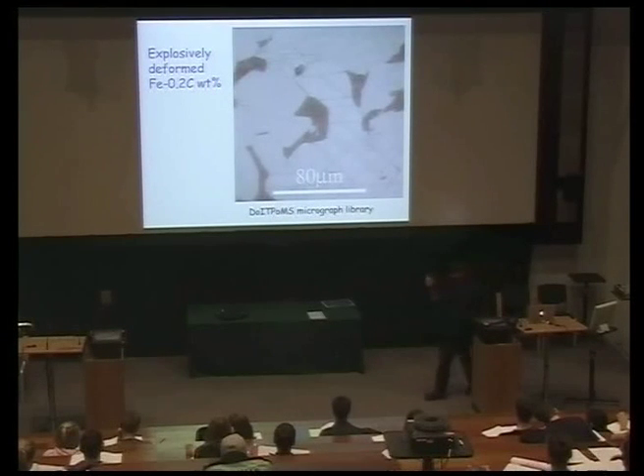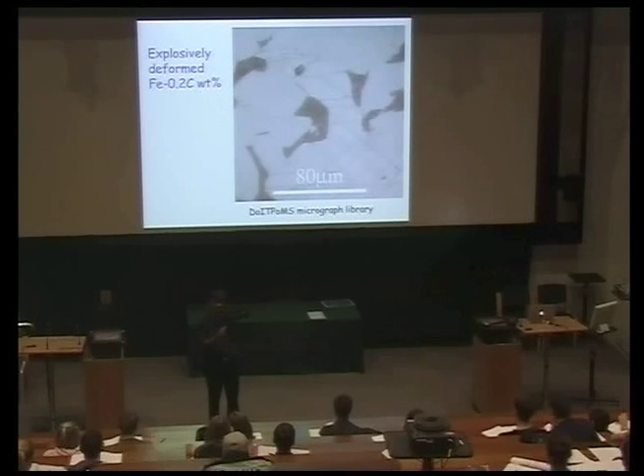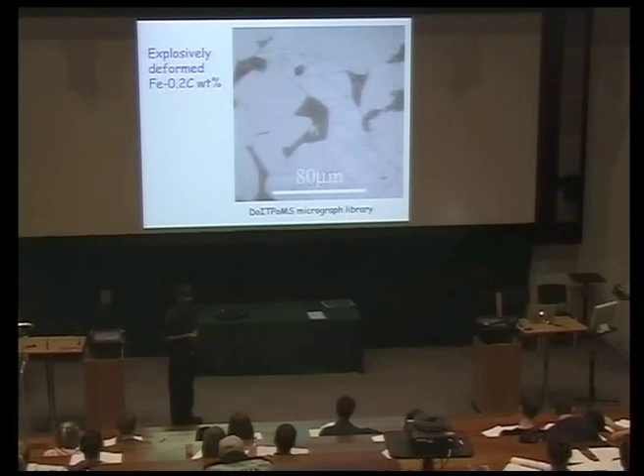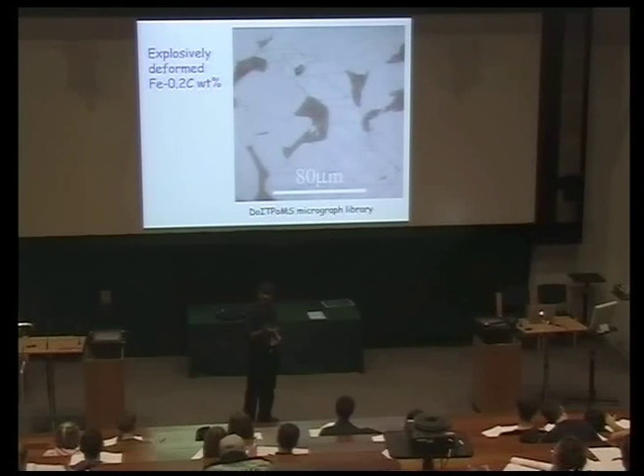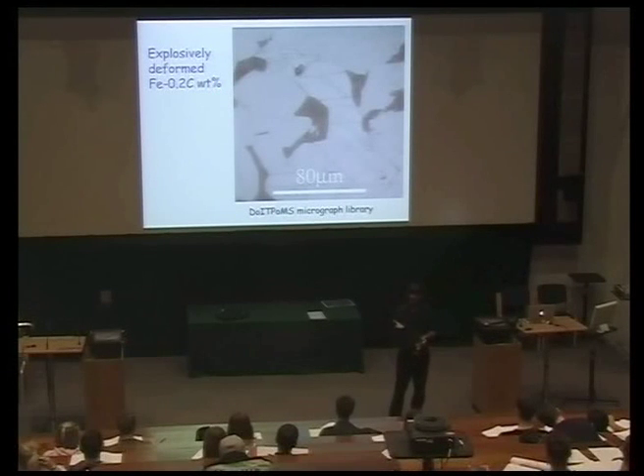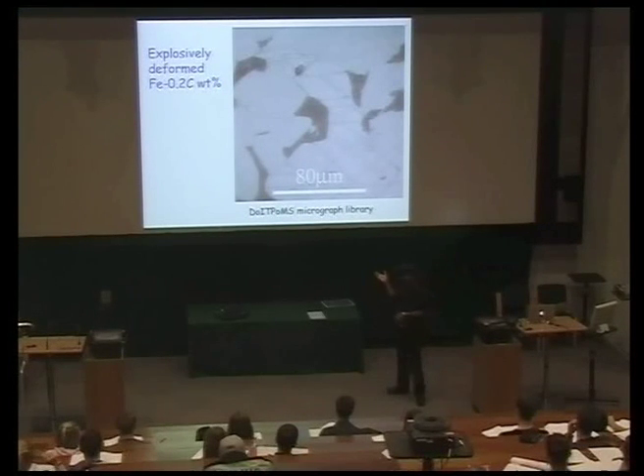This is a piece of ferrite-pearlite steel which was deformed using plastic explosives — of course in very controlled conditions — and you can see mechanical twins. If you deform steel ordinarily, you will not get these twins; it will deform by slip. You can use this for forensic evidence: sometimes when you have a crash or an explosion, you can examine the metallography and look at the strain rate of the deformation, because when you blow something up it's a very high strain rate deformation, and you can pick up mechanical twinning.